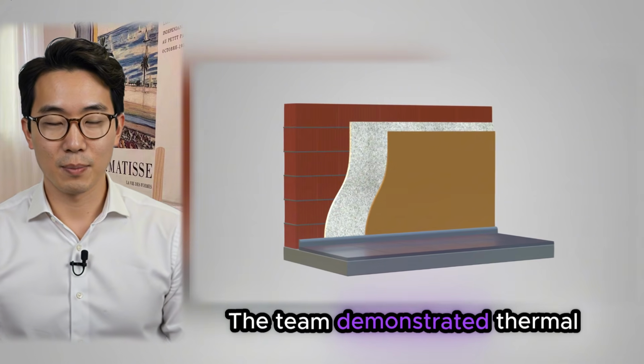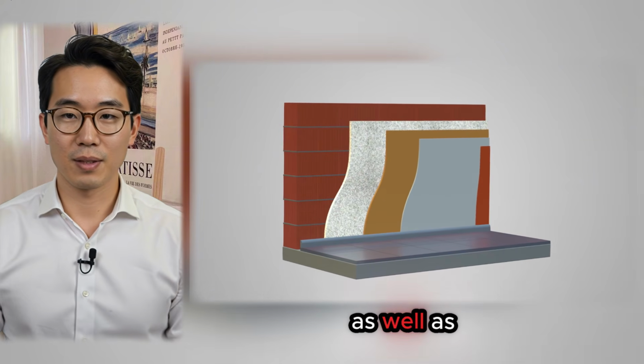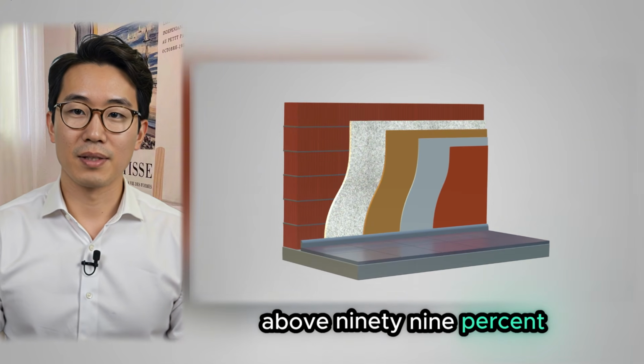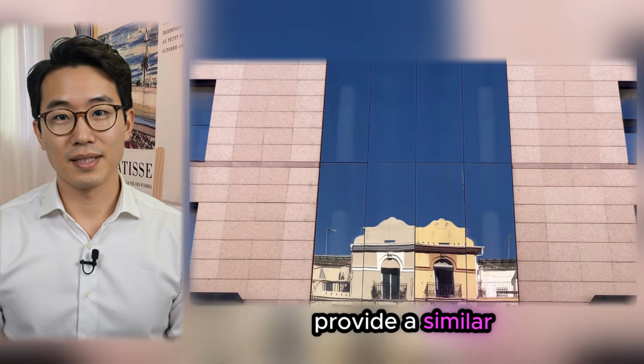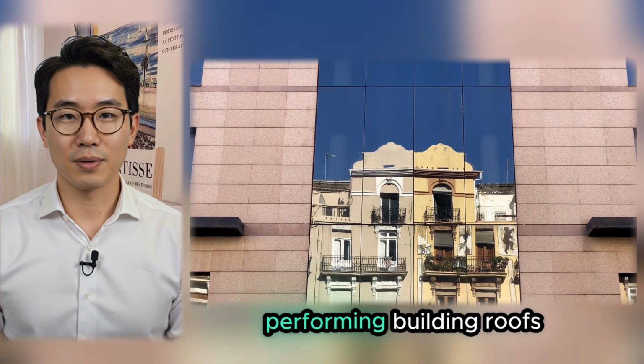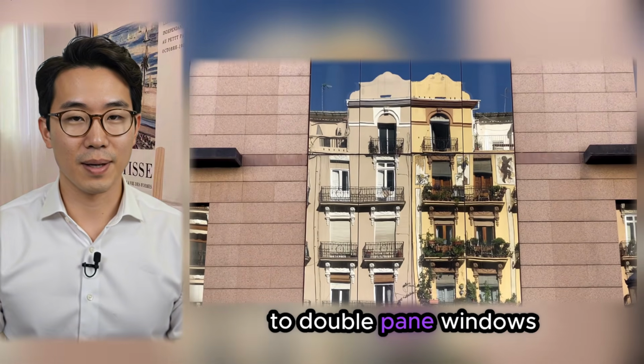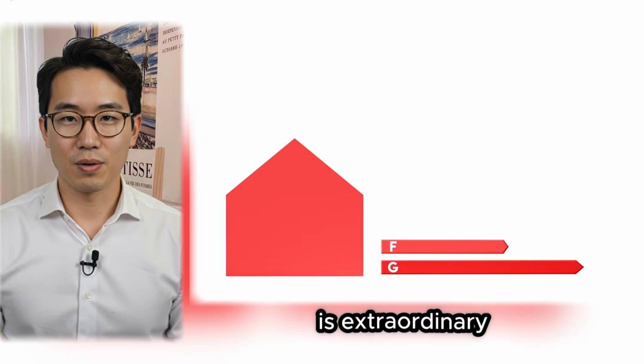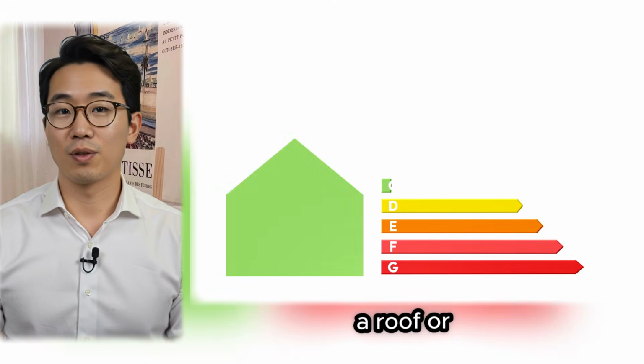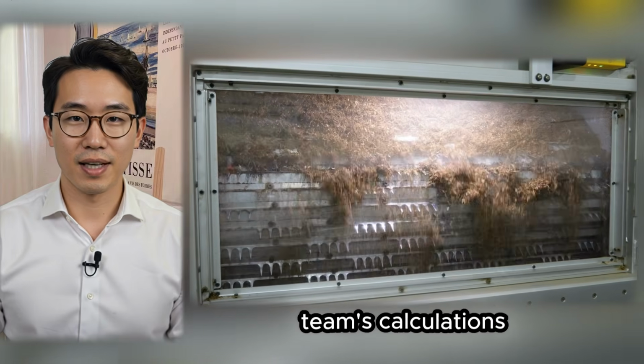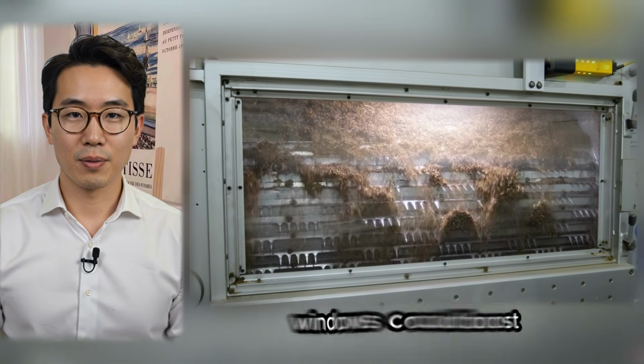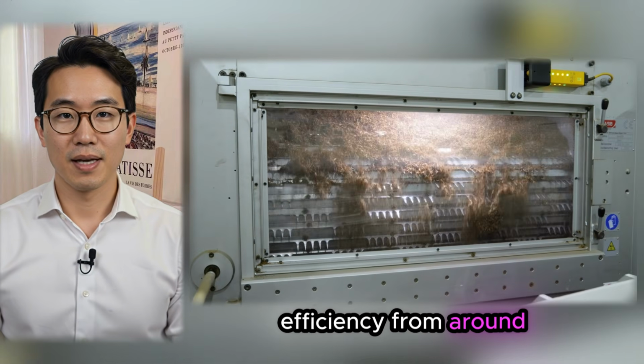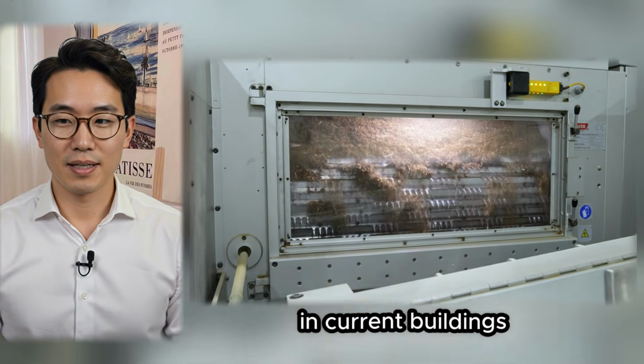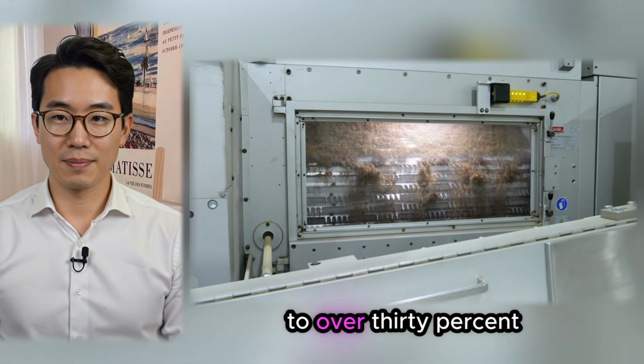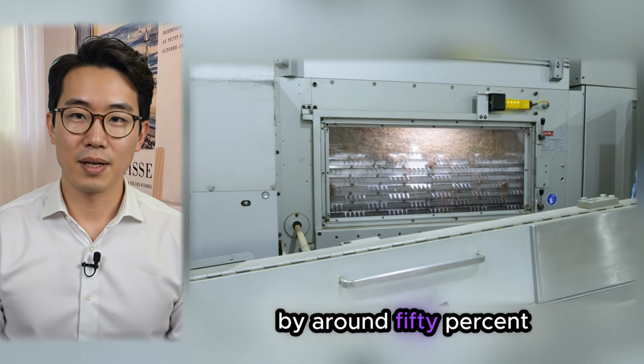The team demonstrated thermal conductivity lower than that of still air, as well as an average light transmission above 99%. And Mochi glass units can provide a similar rate of heat transfer to high-performing building roofs and walls with thicknesses comparable to double-pane windows. That last sentence is extraordinary. A window that insulates as well as a roof or a wall while remaining clearer than ordinary glass. According to the team's calculations, a building retrofitted with Mochi windows could boost its energy efficiency from around 6%, a typical value in current buildings, to over 30%, while reducing the heat energy passing through by around 50%.